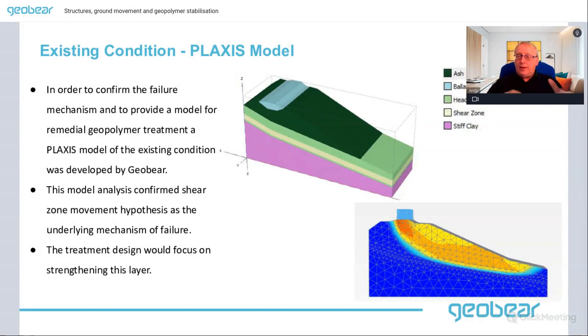Now, in order for us to confirm that, we were given a site investigation. And so we built a Plaxis model to see if we could replicate the movement that was being shown, and then try and determine what the factor of safety was of the overall embankment. This shows the Plaxis model that we developed, and the model confirmed the position of the shear zone and the movement along the shear zone. So we essentially had a layer of very, very weak clay along which the whole embankment was sliding over towards the river. And so the treatment design was to focus on strengthening this weak layer. It wasn't really the whole of the embankment. The real issue was a particularly weak layer underneath the embankment.